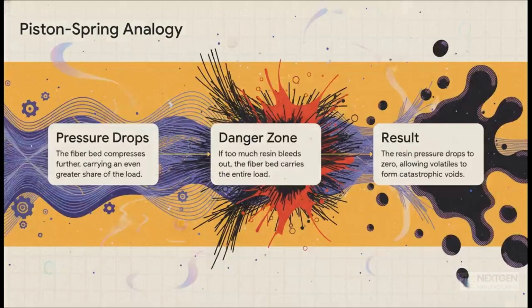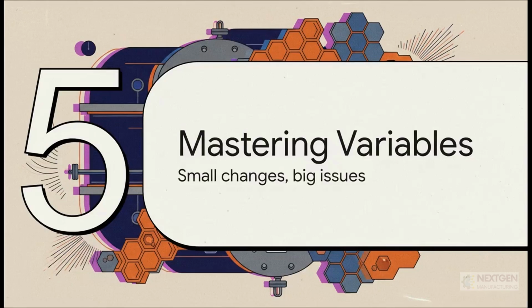So as more and more resin escapes, that fiber bed carries more and more of the weight. And this is the danger zone. If too much resin bleeds out, the fiber bed compresses completely and ends up supporting the entire load all by itself. And the result? The pressure in the liquid resin plummets to zero. With nothing holding it back, any trapped moisture flashes instantly into steam, creating massive, part-killing voids. So you see, the whole game is about preventing that pressure drop. And to do that, you have to master a whole bunch of interconnected variables where honestly, even the tiniest changes can lead to huge problems.